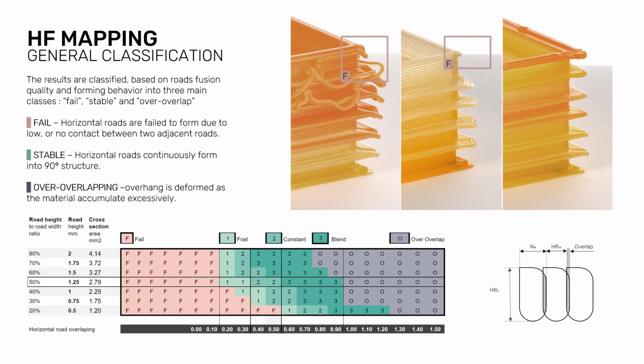The results are classified based on road fusion quality and forming behavior into 3 main classes. Fail represents the parameters when horizontal roads fail to form, due to low or non-contact between 2 adjacent roads. Overlap is defined when the overhang is deformed as a result of material accumulating excessively. Stable is classified when horizontal roads are continuously formed in a 90-degree structure. However, those structures have different fusion qualities and were classified into 3 additional classes.